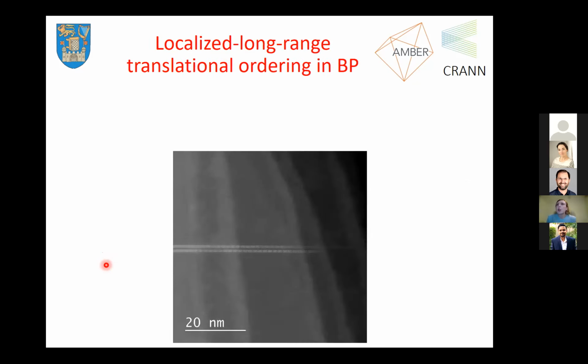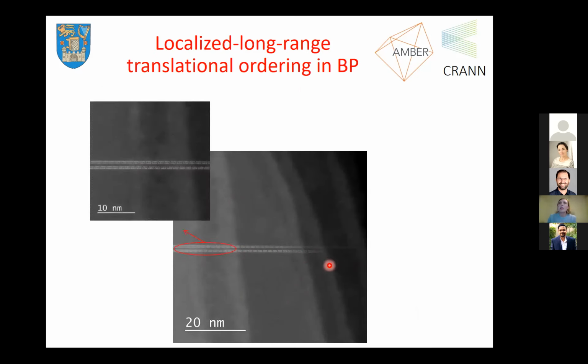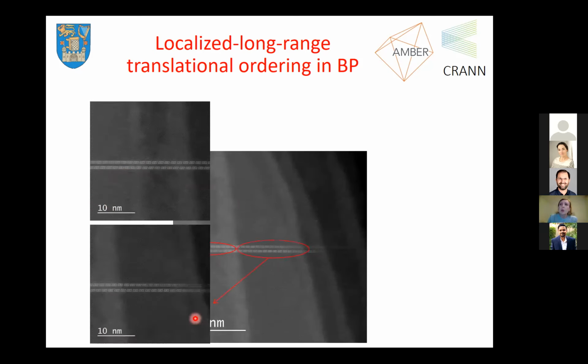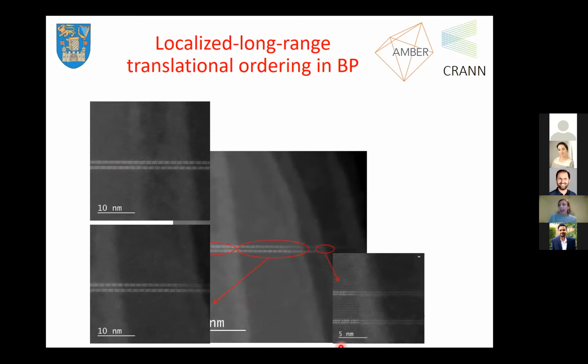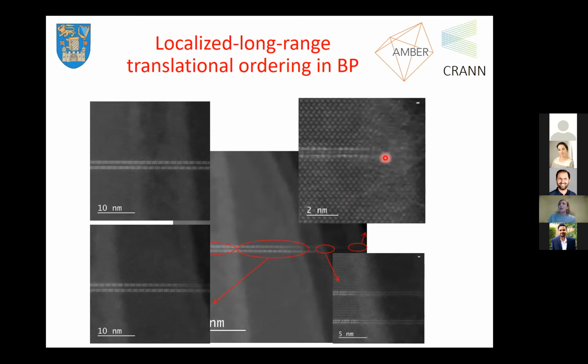So we went to the aberration corrected STEM, and we were amazed to see these lines being so regular. You can see here the black phosphorus steps: here you have a monolayer, 2 layers, and here a little bit thicker. What was beautiful to see was how structurally perfect these lines were. I'm going to zoom in, and you're going to see the repetition of the unit cells, how structured that is. And this was going on and on until the end of the flake, where the flake was finishing. So this was extremely surprising.